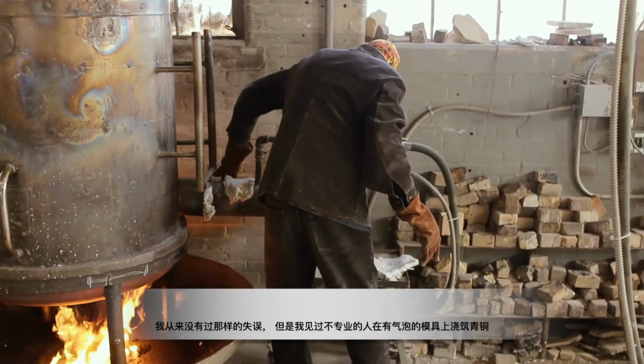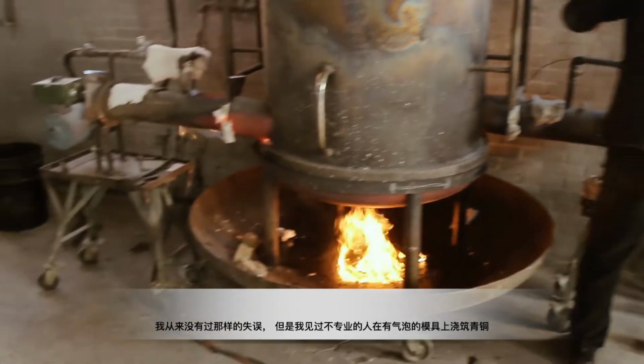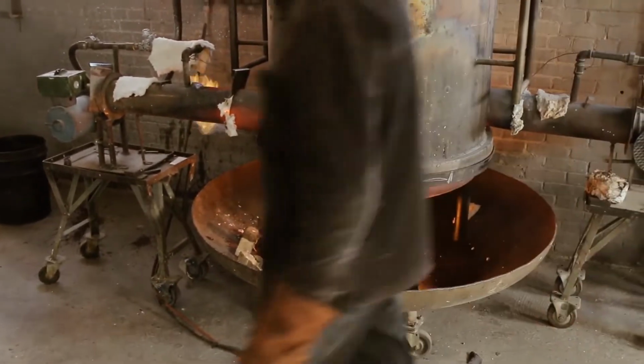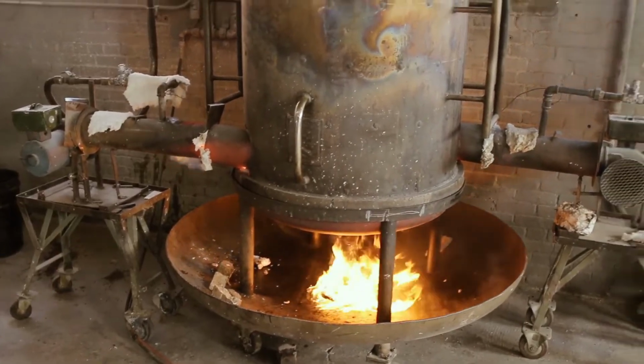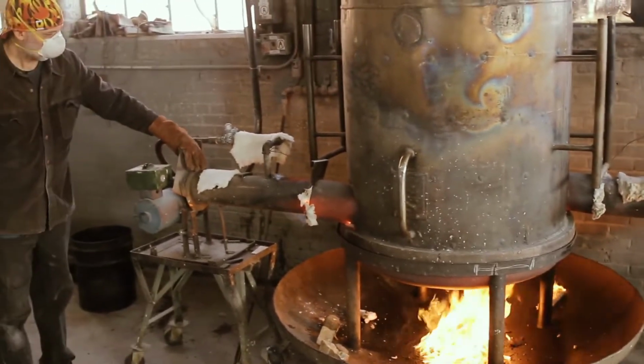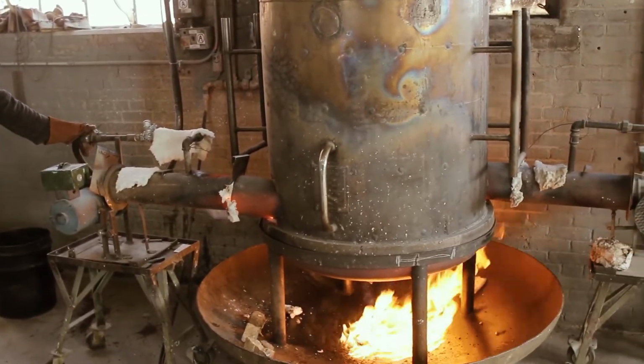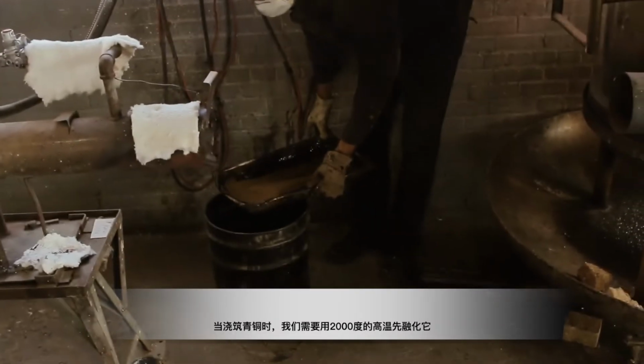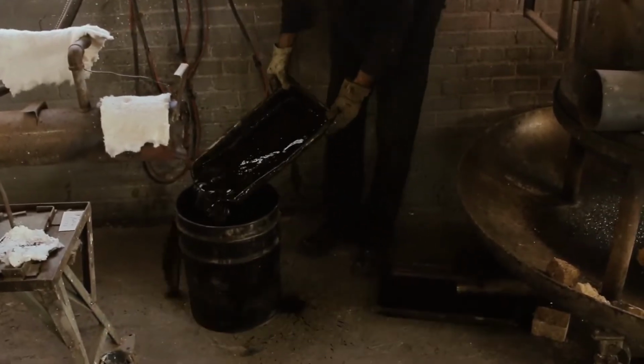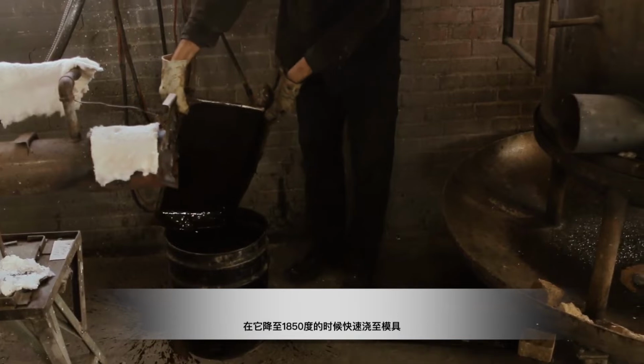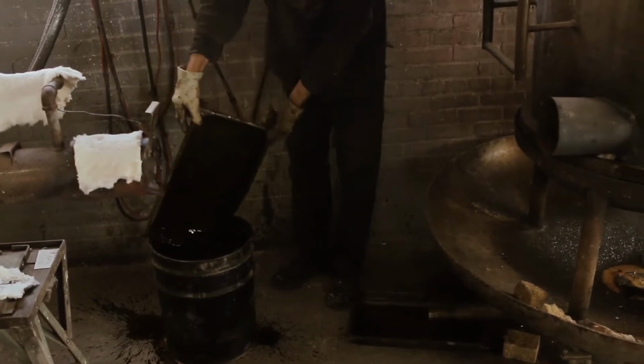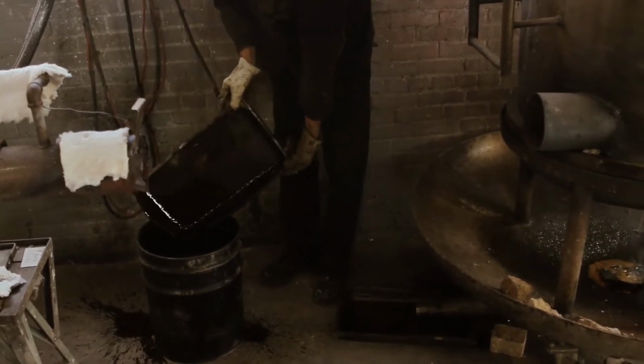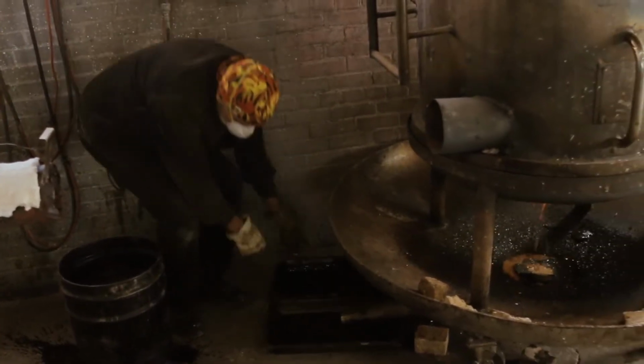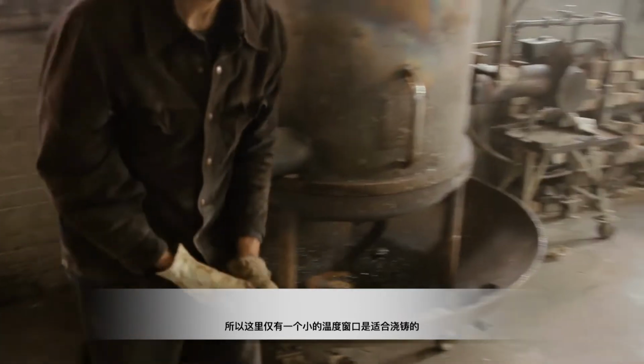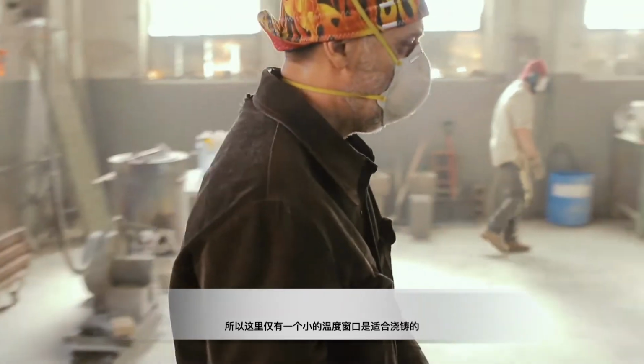I've never had that happen, but the thing is I have seen imperfections based on wax bubbling into the metal before the metal solidified. We'll be pouring the bronze, we melt it to about 2,000 degrees and pour soon thereafter, and bronze literally solidifies at 1,850 degrees. So it's a small window of temperature that we're working in.